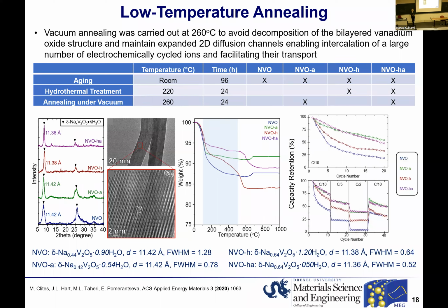And what this tells us as a scientific community is that when we think about different electrode materials, we must realize that as we start studying new phases, we may need to revisit the electrode processing approaches. For example, the standard drying temperature for the electrodes in non-aqueous energy storage devices is 105 Celsius, just in order to remove surface water. Now we have structural water, so this drying temperature might not be sufficient, and we might need to increase the temperature of electrode drying in order to see better results during battery cycling.